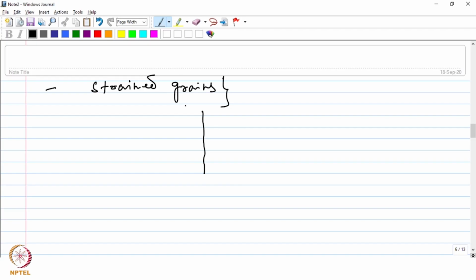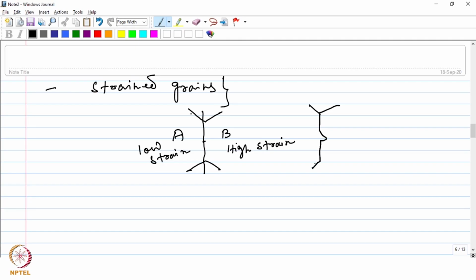Okay, so let's say you have this boundary between two grains A and B, grain A has low strain and B has high strain. So there is a gradient in the strain energy along this boundary. Okay. So it will try and reduce the energy. So therefore, this boundary can bulge into the high strained region in this manner. A small bulge like that can be created due to this strain energy gradient.